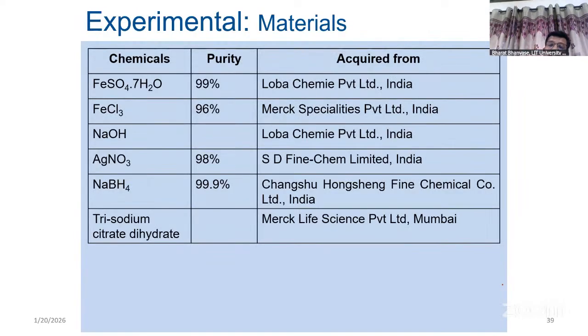So if you see the experimental part here - FeSO4, FeCl3 addition, then NaOH was used, AgNO3 was used, sodium borohydride was used. And then trisodium citrate dihydrate was used as a surfactant.